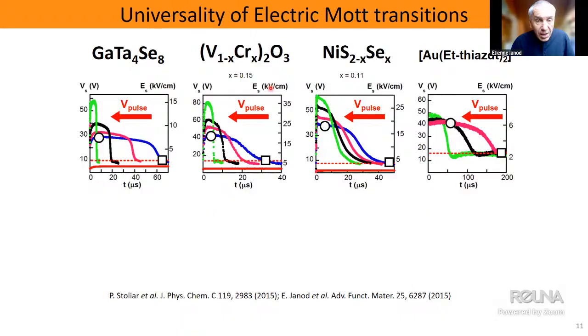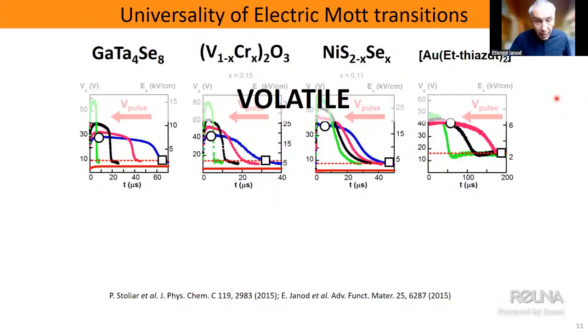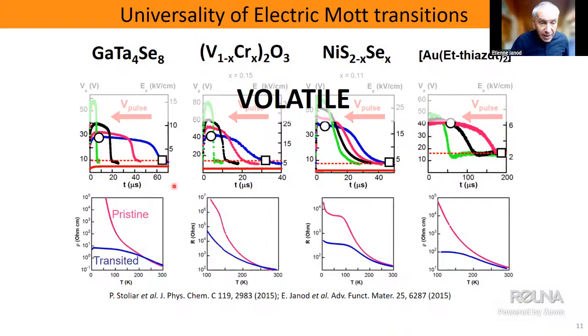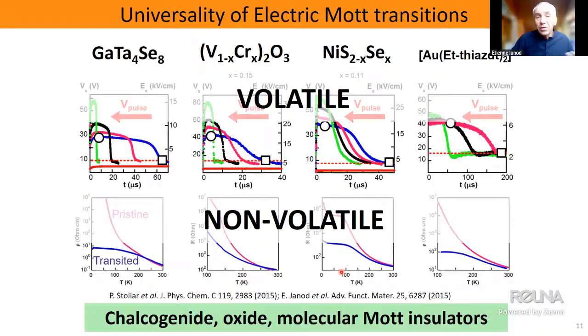This oxide, V2O3, it works. It works also on another canonical Mott insulator, nickel disulfide, substituted with selenium. You see here the drop of resistance, but it works also on a molecular Mott insulator. This is the example shown here. This is universal for the volatile part that I show here, but it's also true for the non-volatile. Here I present resistance versus temperature measured before in red or after in blue the application of the electric pulse, and you see that after the non-volatile transition, we have a permanent decrease of the resistance. So this property is universal in all Mott insulators. They can be chalcogenide, oxide, or molecular. It seems that it doesn't matter, let's say. All right.